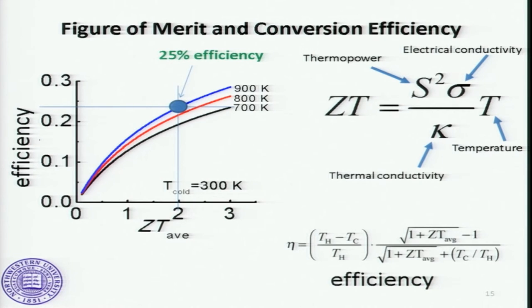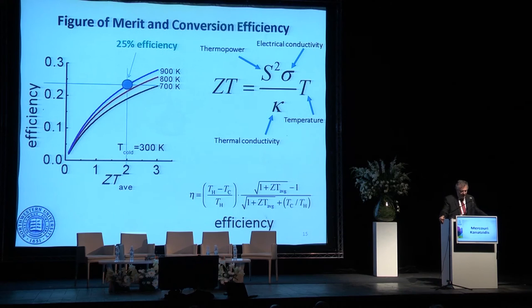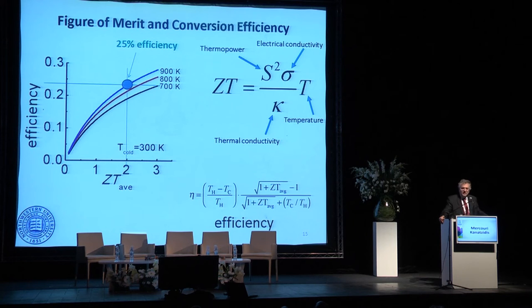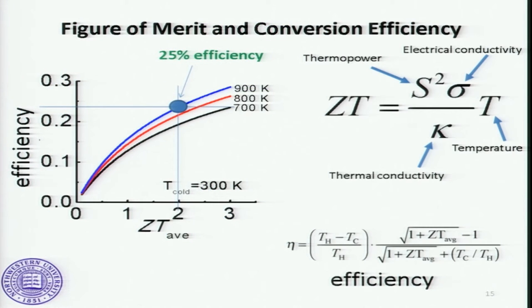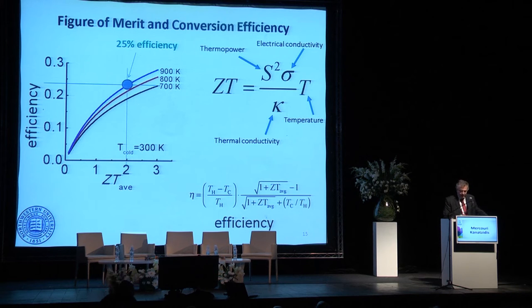The ZT then is related to the efficiency equation in the lower right. And so the efficiency is well known and calculated. In this plot, you can see how ZT and efficiency are related. For example, for a hot source at about 800 to 900 K, with a ZT of about 2, you can expect to make a generator of about 25% conversion efficiency. That's very exciting because we're converting low-quality energy into high-quality energy, and that's what makes people excited in this area. The old materials, the ones that NASA has been using, have a ZT of about 0.7 to 0.8 in this graph. So you can see the efficiencies are about 6 to 7% at best. So we're looking for materials that have high thermopower, high electrical conductivity, and low thermal conductivity.